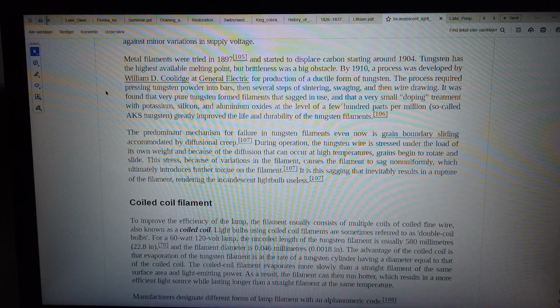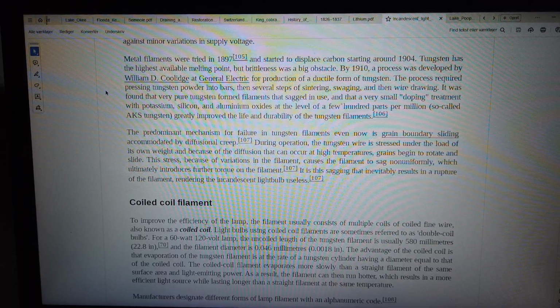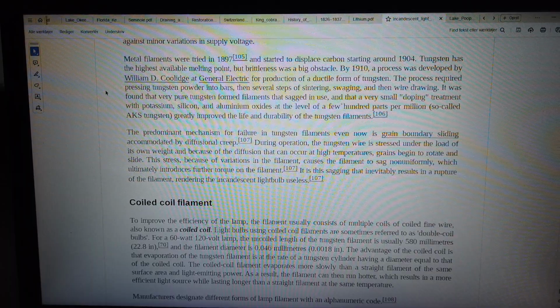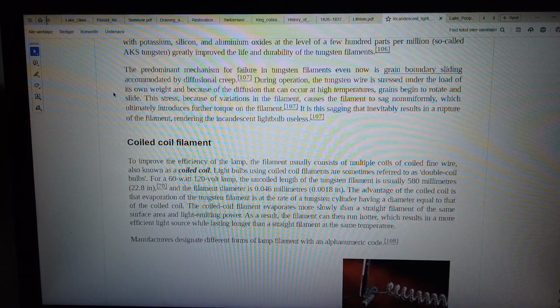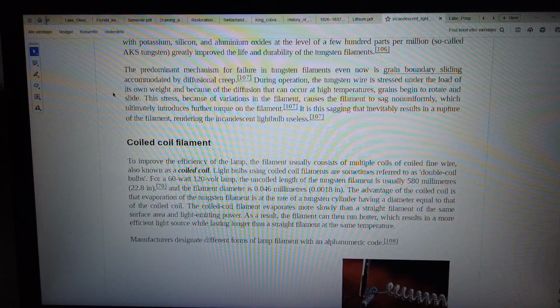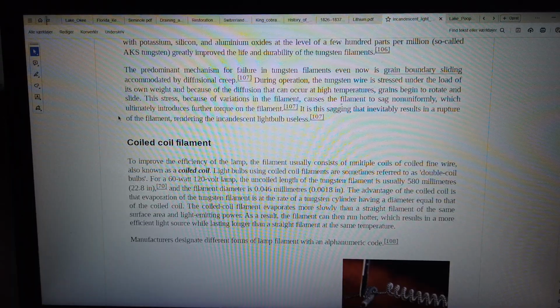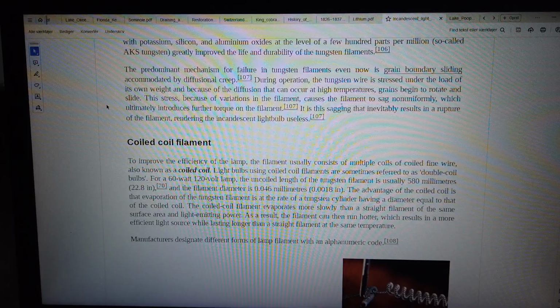The predominant mechanism for failure in tungsten filaments even now is grain boundary sliding accommodated by diffusional creep. During operation, the tungsten wire is stressed under the load of its own weight, and because of the diffusion that can occur at high temperatures, grains begin to rotate and slide. This stress, because of variations in the filament, causes the filament to sag non-uniformly, which ultimately introduces further torque on the filament. It is this sagging that inevitably results in a rupture of the filament, rendering the incandescent light bulb useless.